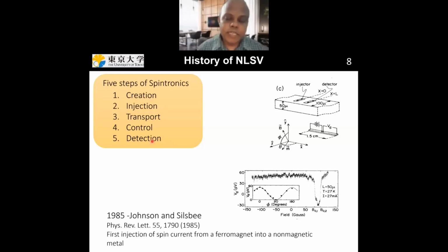The first experimental realization of a spin current injection into a metal was in 1985 by Johnson and Silsbee, where they could inject spin current into a bulk piece of aluminum using ferromagnetic electrodes. They could make a non-local spin valve device, and they found that when the two ferromagnets are parallel, they have a positive voltage, and when they are anti-parallel, they have a negative voltage. This was the first non-local spin valve device that was fabricated.